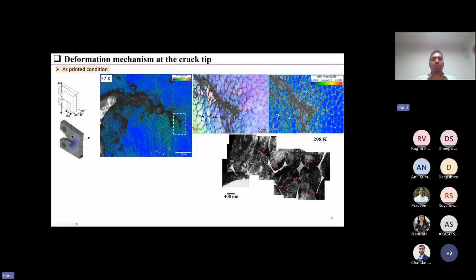So essentially what is happening is that in the early phase of plastic deformation, these cell boundaries are able to resist plastic deformation. But in case of severe plastic deformation at the crack tip, these nano bridges connecting the B2 phase break down and allow the movement of these dislocations away from the crack tip. So you are able to distribute damage away from the crack tip, and at the same time you are also able to have high strength in this microstructure.